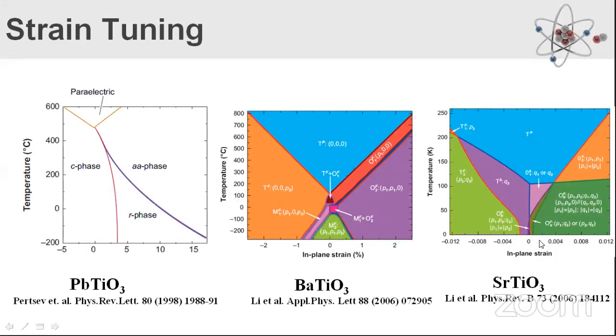If you slightly change the strain, you can change between orthorhombic, tetragonal or monoclinic structure. And you should note down that the temperature here is on the Kelvin scale, not on the centigrade scale. All these are below room temperature, and at 0 Kelvin this is called a quantum paraelectric material. I don't want to get into the details of quantum paraelectricity. This is how we can tune the material property by applying in-plane strain.